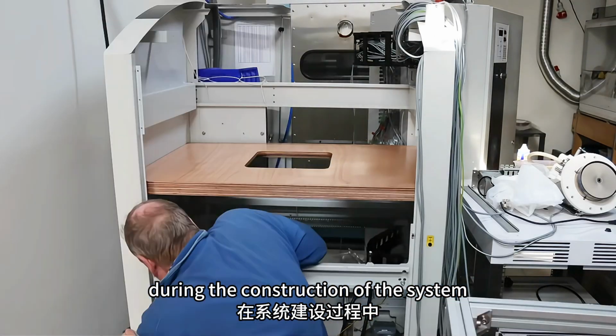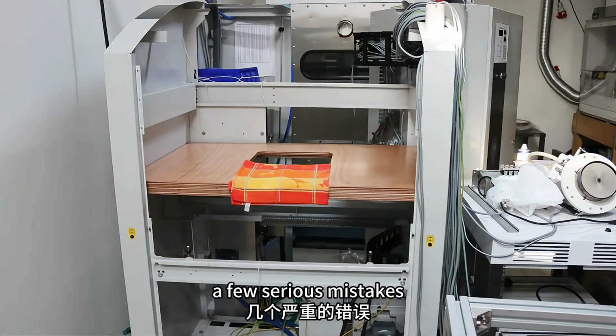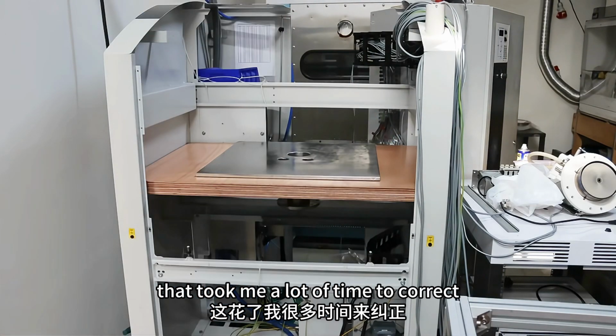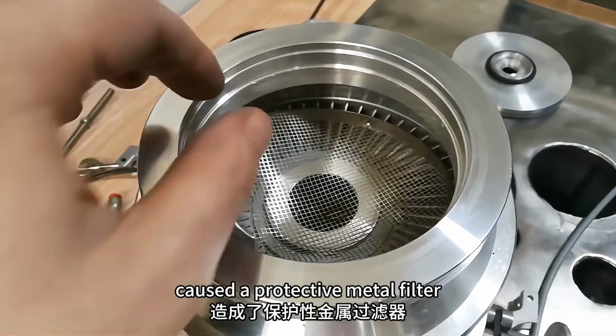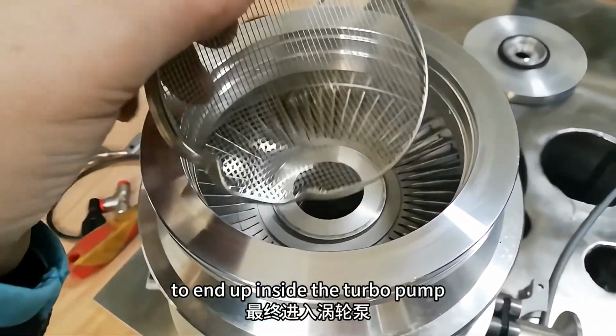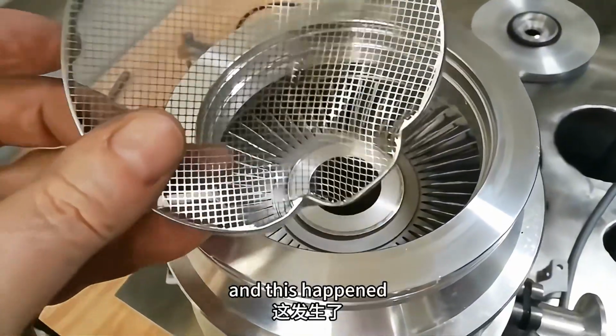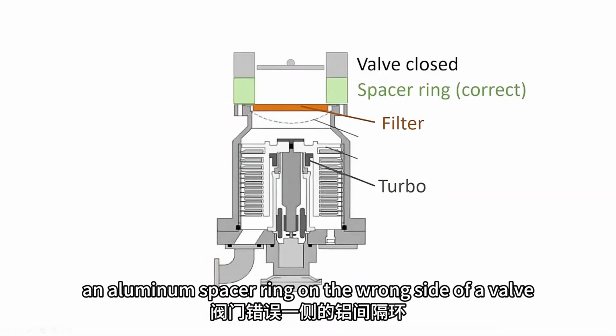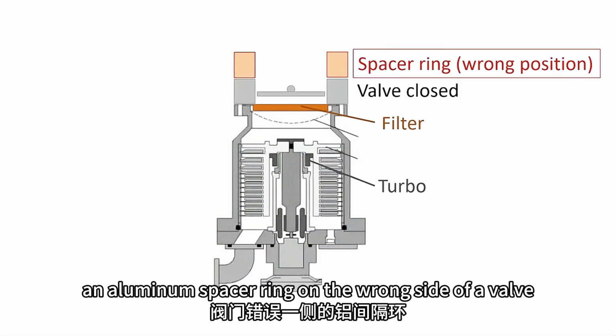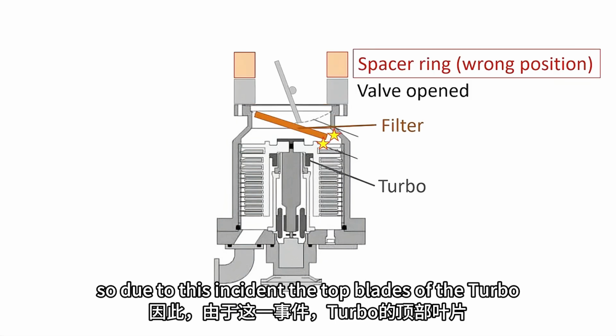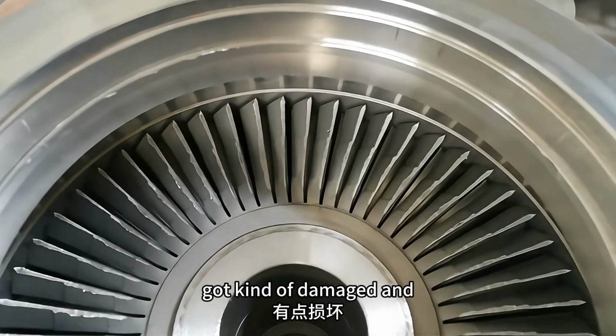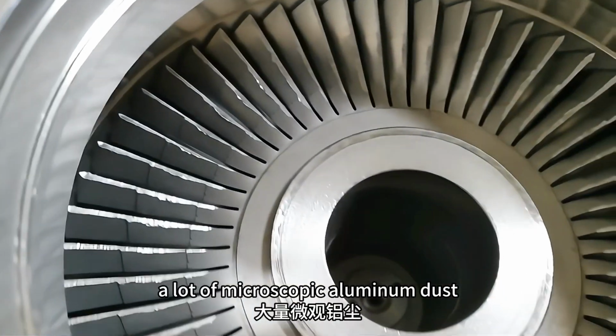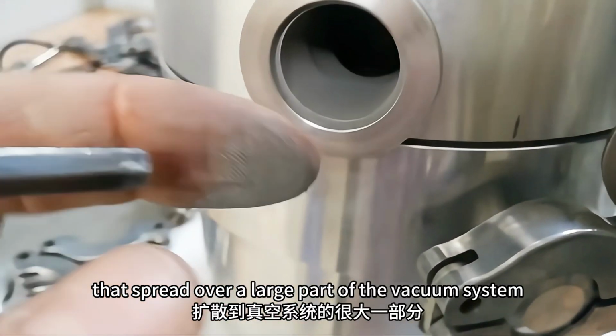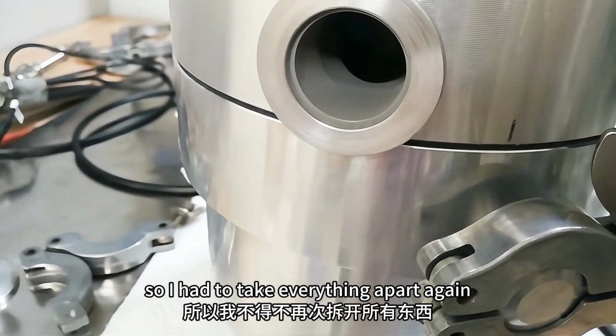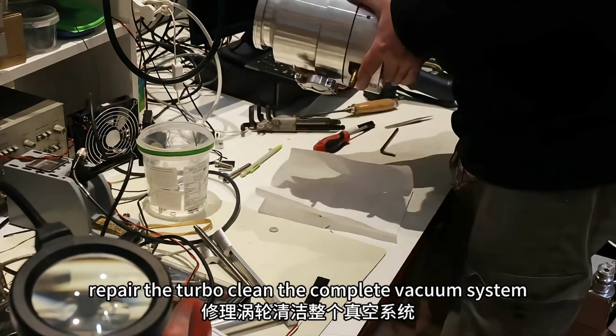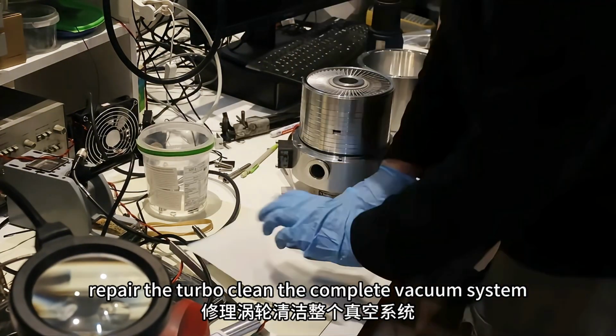Now, during the construction of the system I actually made a few serious mistakes that took me a lot of time to correct. And one of these errors caused a protective metal filter to end up inside the turbopump while running at 50,000 RPMs. And this happened because I placed an aluminum spacer ring on the wrong side of a valve. So due to this incident, the top blades of the turbo got kind of damaged, and it also generated a lot of microscopic aluminum dust that spread over a large part of the vacuum system. So I had to take everything apart again, repair the turbo, clean the complete vacuum system, the works.